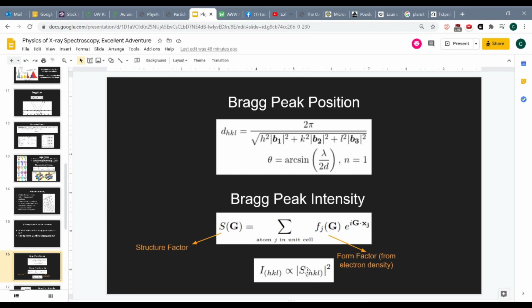So for certain HKL values, which tell us where our theta values are going to be, because that's what our distance between planes is, we can figure out what the magnitude is. The structure factor is defined as a sum over all the atoms in the unit cell of first what's known as the form factor, which is basically some constant value calculated from the electron density of whatever atom the photon's interacting with, times some exponential, which is in terms of the reciprocal lattice and whatever lattice plane you're using.